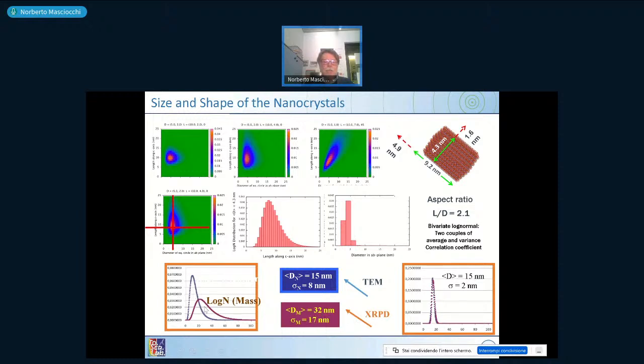But these two curves are mathematically possible to interconvert. So the information you get from X-ray is giving correct numbers. The one from TEM gives the correct numbers, but you should know that the correct numbers are associated to counting or to weighing, which is different in the two cases. Only if the two systems are highly monodispersed, then the two curves are nearly coinciding.